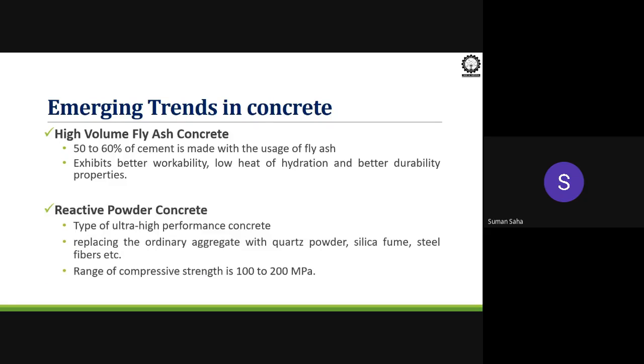Next is reactive powder concrete. It can be called ultra high performance concrete. As I told earlier, its compressive strength range is 100 to 200 MPa. But to achieve 100 to 200 MPa concrete, if you want to cast one cube, we should have finer material properly compacted, because there should not be any voids, or any connection of voids that would provide paths for cracks.